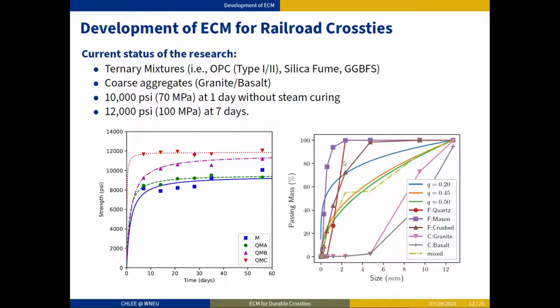So basically, we had the size distribution of the individual aggregates, and by mixing all those different types of aggregates, we try to achieve a specific distribution by controlling distribution parameters. If you see over here, the Q value is between 0.45 and 0.5. As long as we achieve those lines and mix those aggregates with the cementitious material, we achieved 10,000 psi at 1 day and 12,000 psi after 7 days of strength, which is the current status.